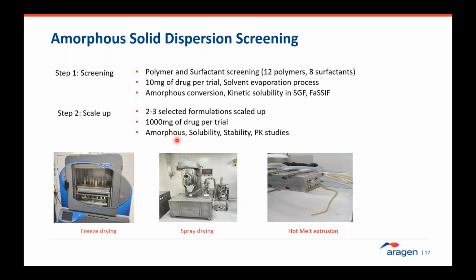And these formulations are thoroughly characterized in terms of solid state, solubility, chemical and physical stability, and also PK studies in different species to confirm and select the best one formulation, which would be used for manufacturing process development. So this process would take typically 4 to 6 weeks, and more than 100 combinations in terms of polymers, surfactant, drug loading, etc. variables are screened to lead up to the one best formulation, which can be developed further into process and then manufactured under GMP.